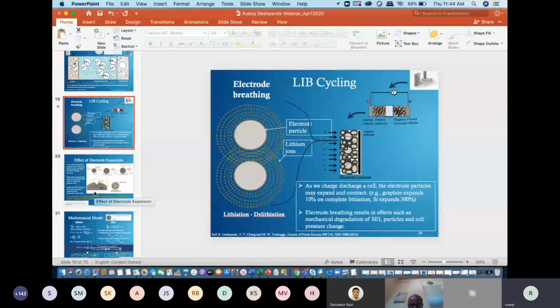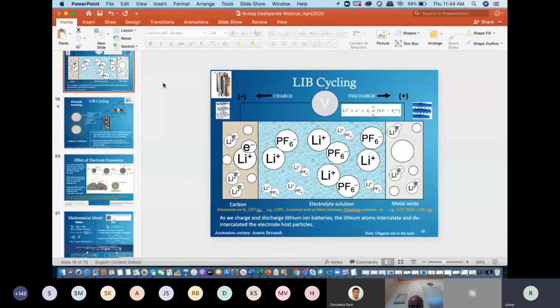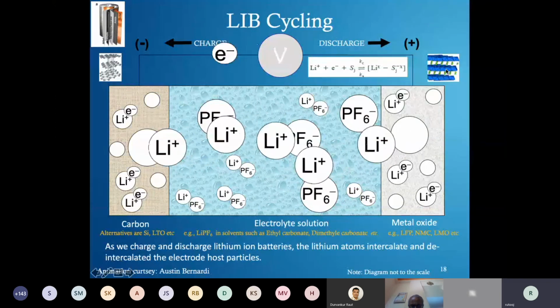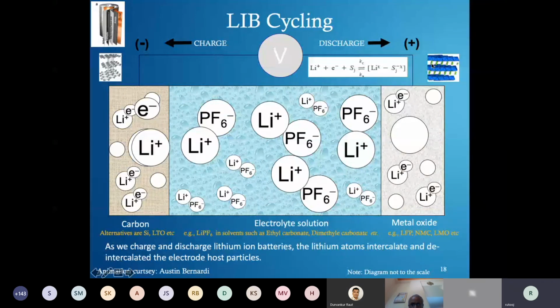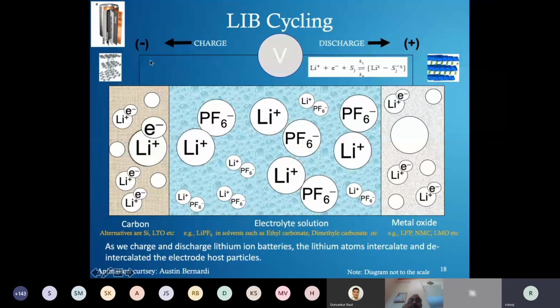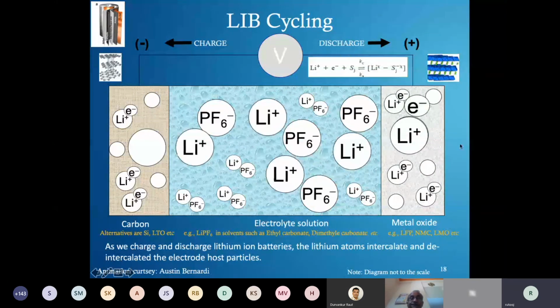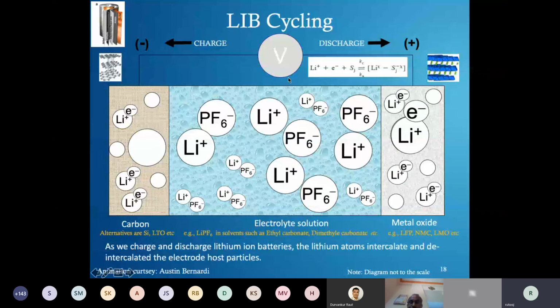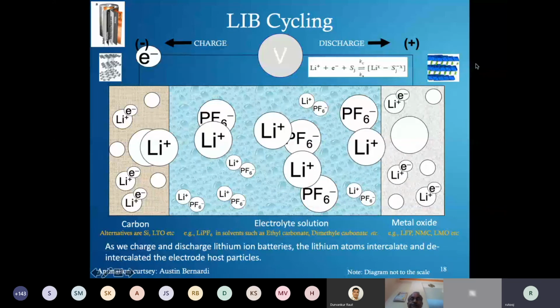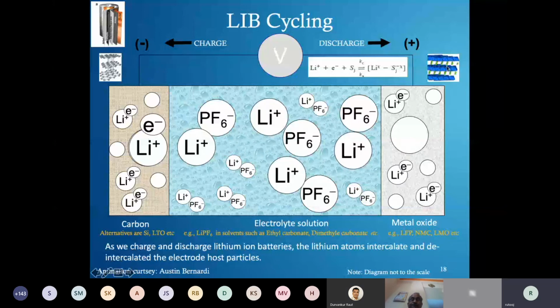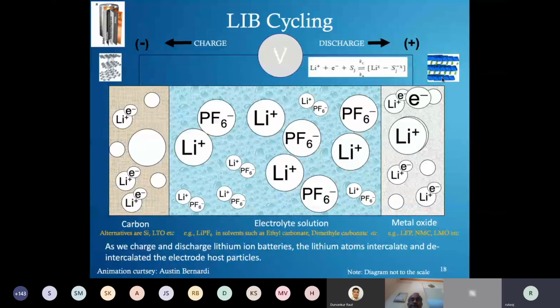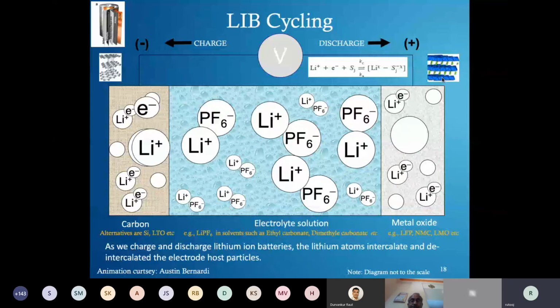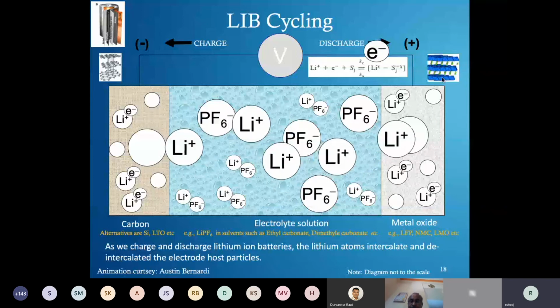Right. So lithium titanate is a crystal. Even with lithium titanate, you can have an LFP or NMC electrode. Lithium titanate is a negative electrode; the positive electrode can be the same LFP or NMC. It doesn't matter. The thing about lithium titanate is it has a crystalline structure, and it has much bigger space for lithium ions to go in and come out. It basically has three-dimensional channels for lithium ions to go in and come out. So it doesn't have any expansion at all, whereas graphite, which is normally used, has 10% expansion. Lithium titanate would not have any expansion.